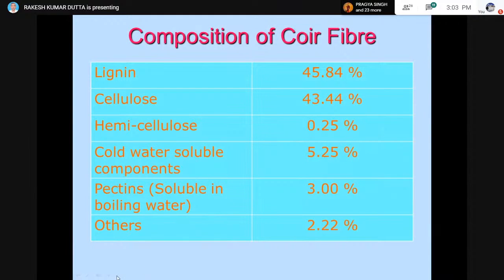Now if we look at the composition of coir fibers, in this slide you see the composition. Lignin is around 45%, cellulose is around 43%, and the rest of the components come out to be around 12% or so. Because of this higher percentage of lignin in the coir, they show better durability in comparison to other fibers such as jute fibers, hemp fibers, and so many other natural fibers. So they show better durability when used in conjunction with soil.